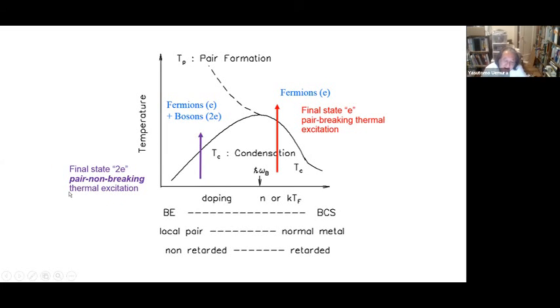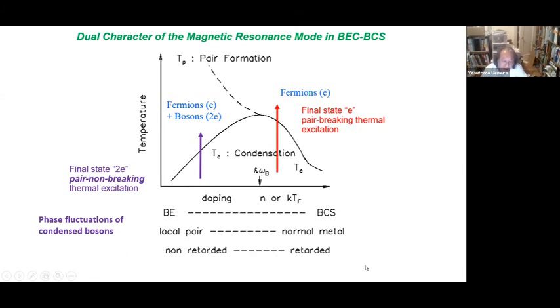And so this is another type of thermal pair non-breaking excitation. Many people say that phase fluctuation in two-dimensional Kosterlitz-Thouless is a pair non-breaking fluctuation, but this is different. This also occurs in 3D, and that is, in my opinion, necessary. Something like this is necessary to account for the thermodynamic transition. So in my opinion, this magnetic resonance mode has a dual character: a pair non-breaking-like situation and the usual pair-breaking-like situation over the evolution in this phase diagram. Okay.